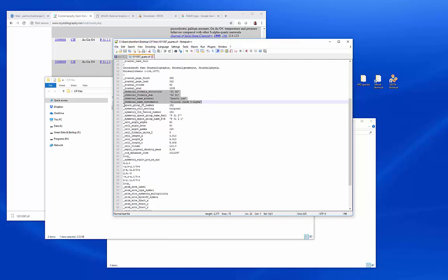The next lines are talking about the space group of the structure. This is the cell setting, but all of these other things are basically just different names for the space group. There's the International Crystallographic Table number, number 152, but that's the same as the Hermann-Mauguin notation, P3 sub 1 2 1. These are just different ways to say the space group of the phase we're going to be looking at today.